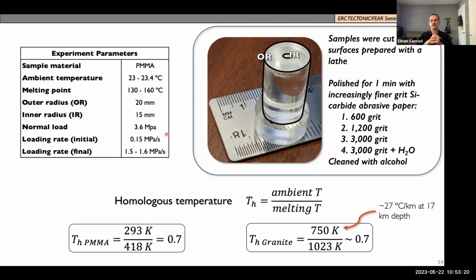We prepare these surfaces just by cutting them and then making them uniform with a lathe. And then we polish them for 1 minute with increasingly finer grit silicon carbide paper, and then ultimately using water to create a slurry that can create a really nice polish on the interface. So we have a pristine interface to start with, and then we clean that interface off with some alcohol.